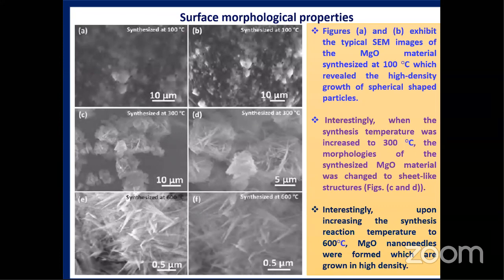When increasing the synthesis temperature to 300 degrees Celsius, you can see the surface morphology is sheet-like. This is the sheet-like morphology structure, but agglomeration is very low. That means surface energy is lower at 300 degrees Celsius. Again, we can go to 600 degrees Celsius, where you can see a needle-shaped surface morphology. So by changing the synthesis temperature, you can observe different morphologies.